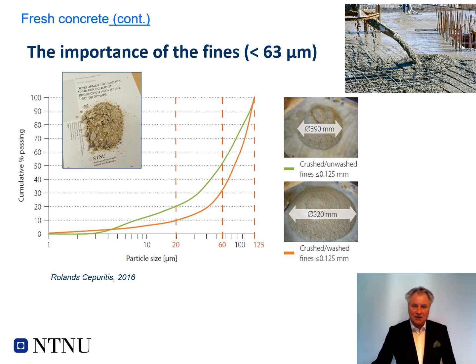So you can see that at 60 micron, the washed one has less content of fines compared to the unwashed. And when you're coming down to 20 micron, these are very, very fine particles, and usually we are not measuring this fineness at all in our ordinary grading curves. You can see in this case, the washed curve got only 10% less than 20 micron, while the unwashed curve gets less than 20%, the double, below 20 micron. And as you can see, it's a big difference on the slump or the flowability of the unwashed one. The unwashed one with a higher filler content gets a much stiffer concrete compared to the washed filler, with less content of the finest of the finest.